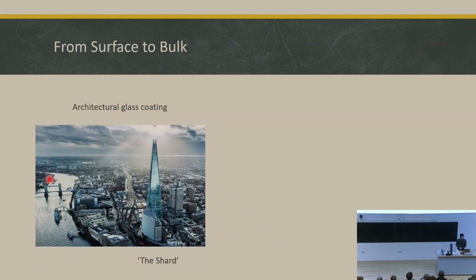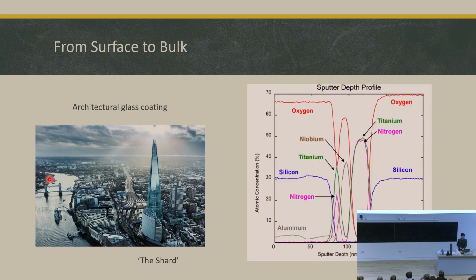Let's look at the example of this architectural glass coating from the Shard. It's a huge building all covered with glass. As I introduced, modern techniques allow us to use argon ion clusters to bombard the surface and etch it layer by layer until we see something beneath the first layers. So how do we read this diagram? If we look from left to right, it goes from the outer surface of the glass to the bulk.